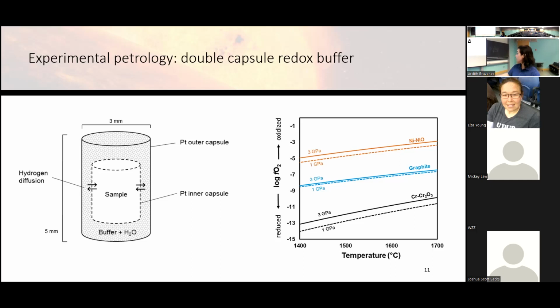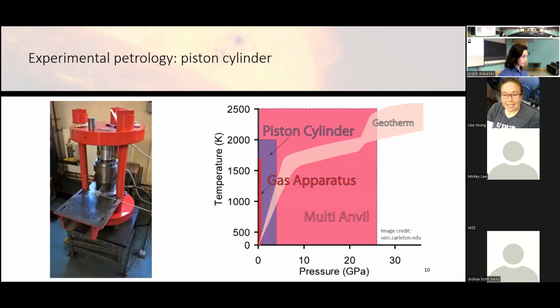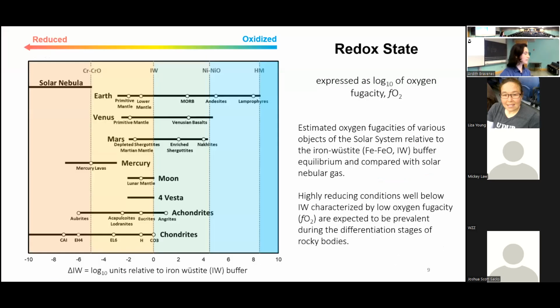And also you can see here on the temperature oxygen fugacity graph, there's 3 different regimes of oxygen fugacity that I'm really going to be talking about. And that's going to be the more oxidized samples around nickel oxide, which represents more terrestrial Earth-like conditions. A somewhat reduced sample near the graphite buffer, which is moderately reduced. And then a very, very reducing redox region near the chromium oxide buffer, which, just to go back for a moment, you can see is approaching the solar nebula in terms of just how reduced it is.